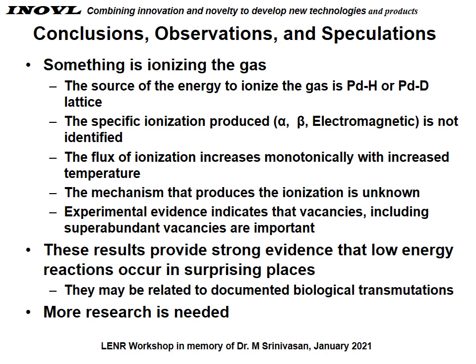Some conclusions, observations, and speculations. Conclusion: something is ionizing the gas. The source of the ionized gas, we know it's the PdH or PdD lattice, but we don't know what the mechanism is. The specific ionization produced, we don't know if it's particulate or alpha, beta, something else, or electromagnetic. It's not identified. The flux of the ionization increased monotonically with increased temperature. The mechanism that produces the ionization is unknown. However, experimental evidence indicates that vacancies, including superabundant vacancies, are important. These results provide strong evidence that low energy reactions occur. They may be related to some of the documented biological transmutations that Jean-Paul Biberian has published several papers on, but clearly more research is needed.